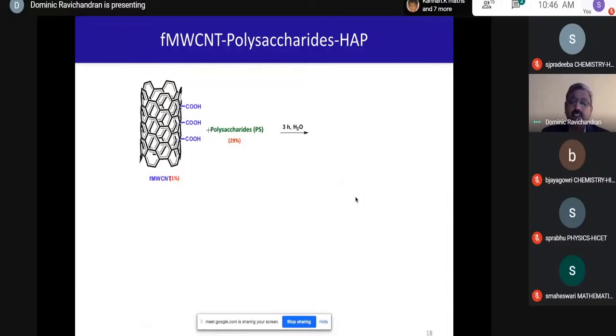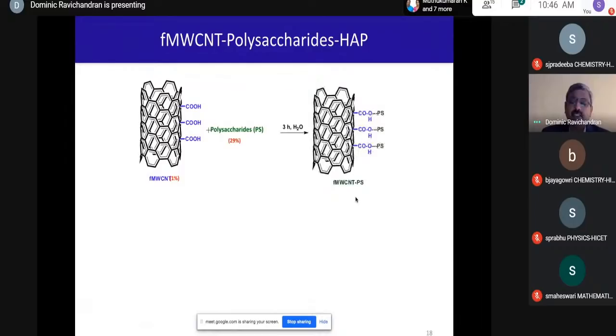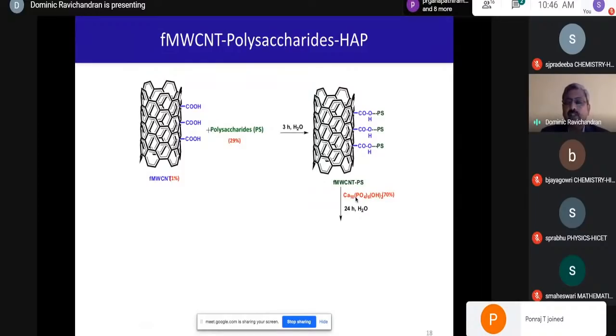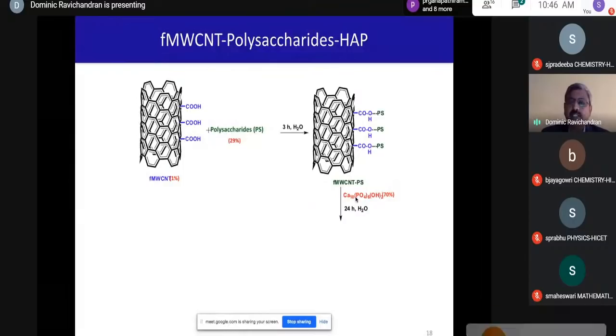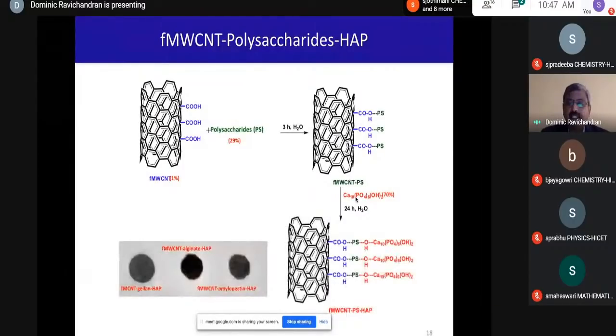In water medium, it was stirred for 3 hours, where the polysaccharides get attached to the multi-walled carbon nanotubes through the functionalization. This is further added with HAP, that is hydroxyapatite, a very well-known ceramic material, and stirred for 24 hours in water medium. This results in a composite, and we create the scaffold of this by the freeze drying method, where these composites are frozen at minus 80 degrees centigrade and lyophilized. These composites can be molded into different sizes based on your requirement.